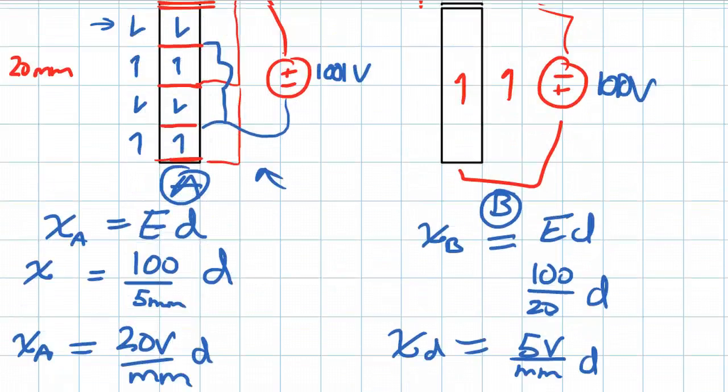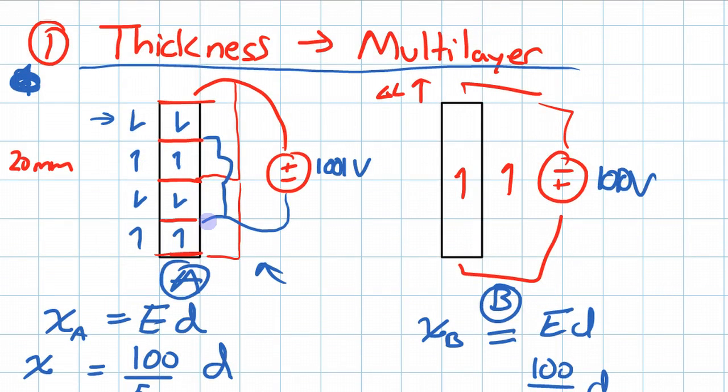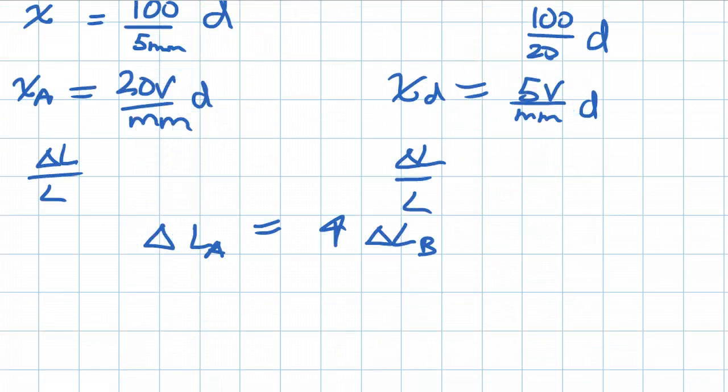So this is one way. Basically, instead of doing 10 or 4 layers, people are going to put in like 100 layers. We can make thicknesses 100 micrometers thick, which is 0.1 millimeters. And we can even make it even smaller, we can make 10 micrometer layers. Imagine how many 10 micrometer layers you can fit in this 20 millimeter. So we can use a relatively lower voltage to get more strain. We'll continue these same ideas in the next video. Thanks for watching.